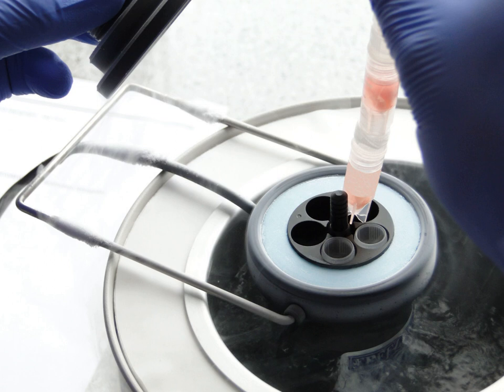To minimize the growth of extracellular ice crystals and recrystallization, biomaterials such as alginates, polyvinyl alcohol or chitosan can be used to impede ice crystal growth, along with traditional small molecule cryoprotectants. That rate differs between cells of differing size and water permeability. A typical cooling rate of about 1 degree Celsius per minute is appropriate for many mammalian cells after treatment with cryoprotectants such as glycerol or dimethyl sulfoxide, but the rate is not a universal optimum. The 1 degree Celsius per minute rate can be achieved by using devices such as a rate-controlled freezer or a